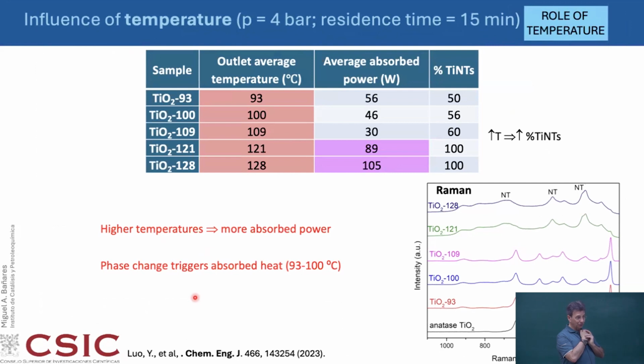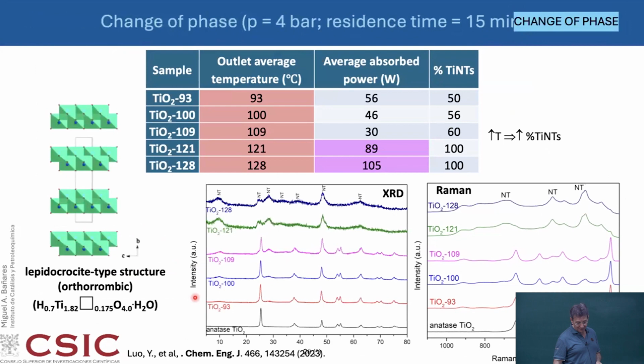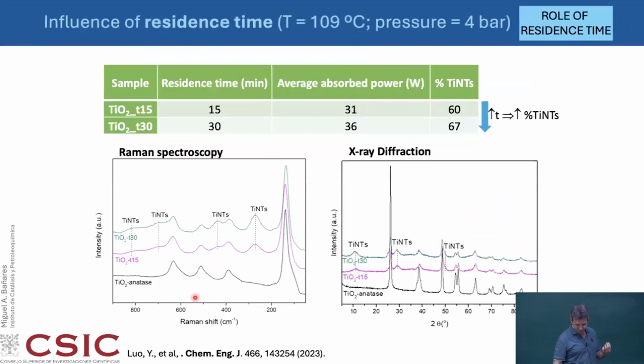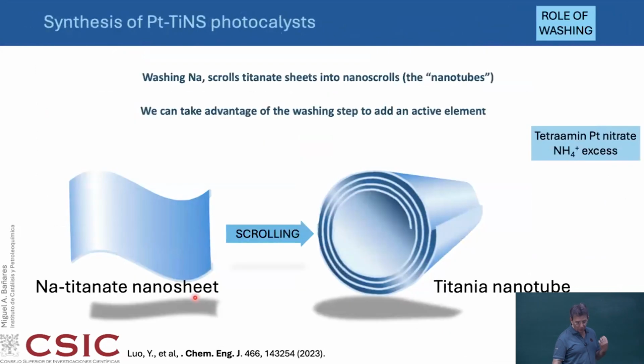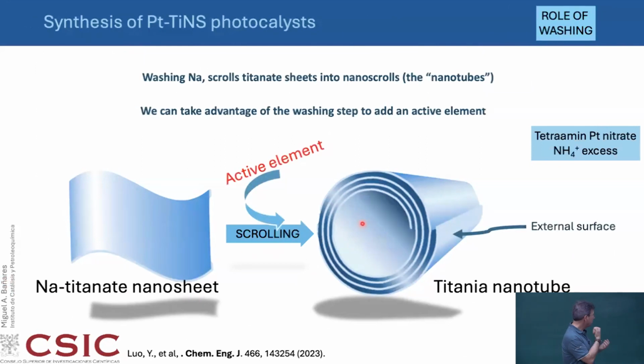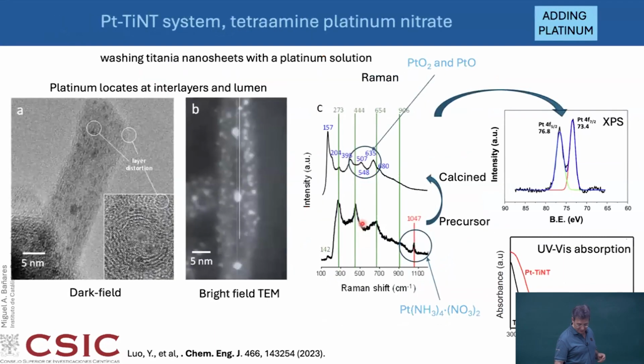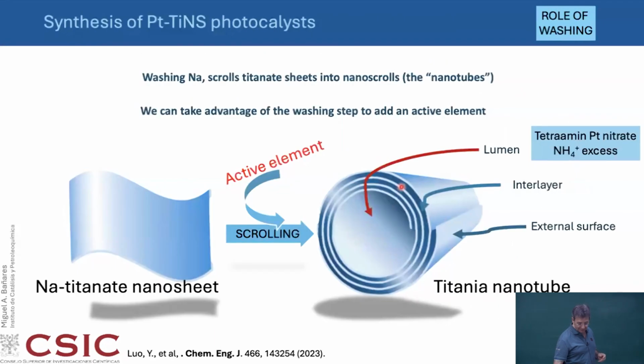Now you want to make photocatalysis, and titanium dioxide is a nice guy, but it is even a nicer guy if you put an active phase on it. So the sheet will scroll into this tube, which is not exactly a tube, but behaves like a tube because it scrolls. So the idea is that we can put, when we are washing, an active element that will enter into it. And we can control whether it goes inside the tube, at the interlayer, or outside.